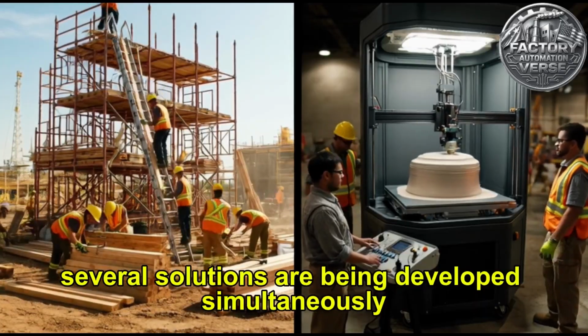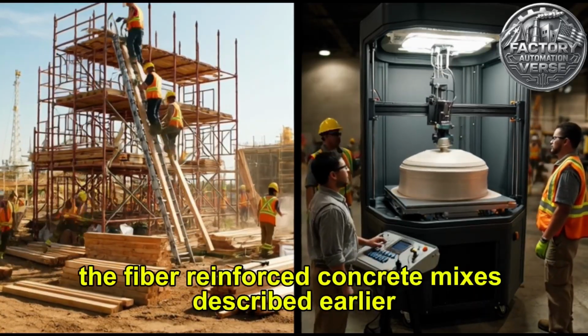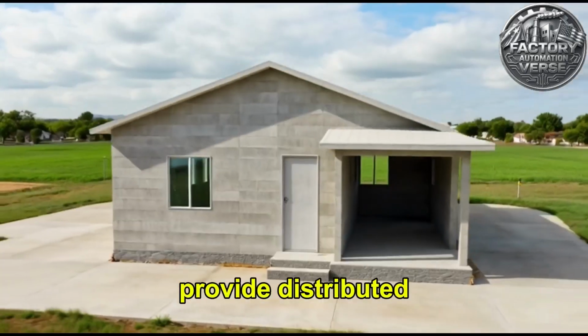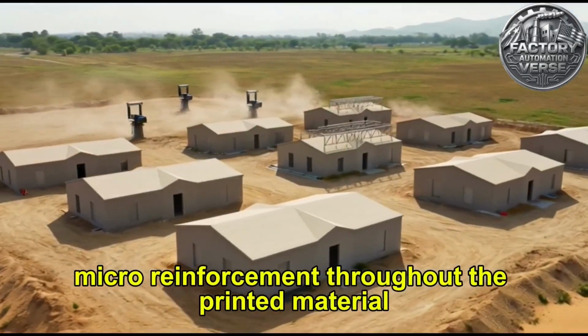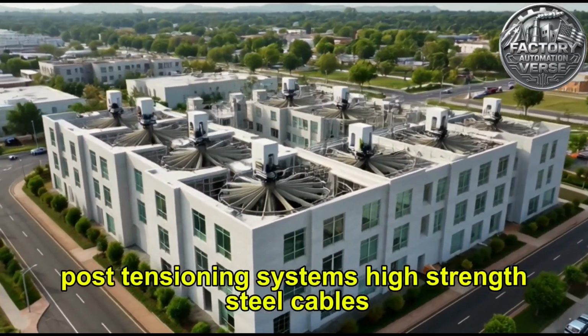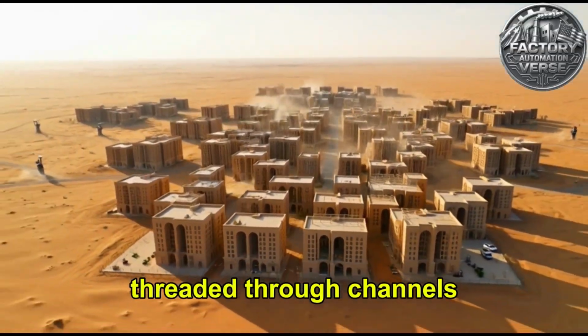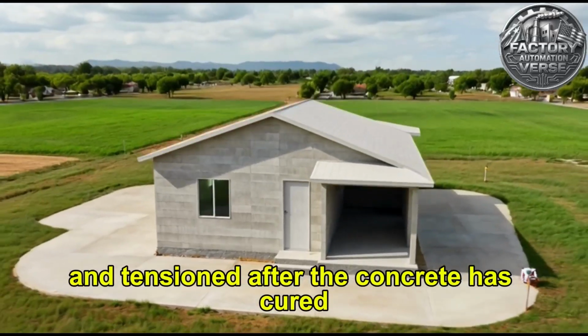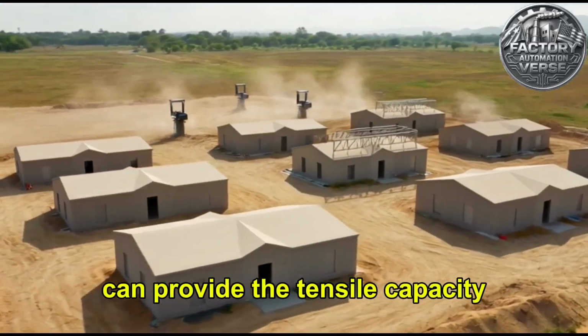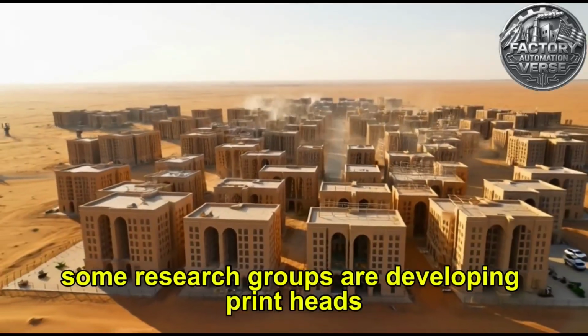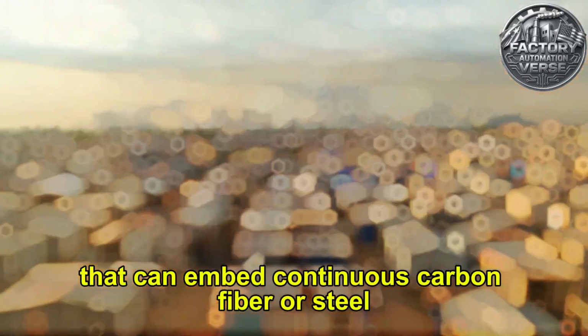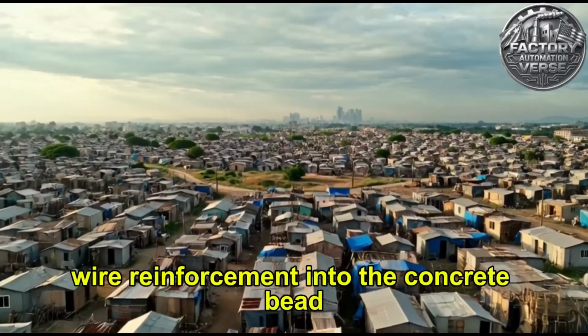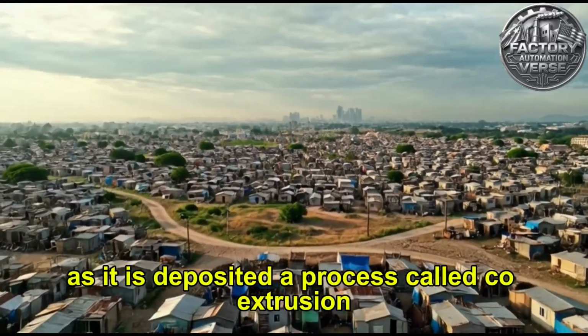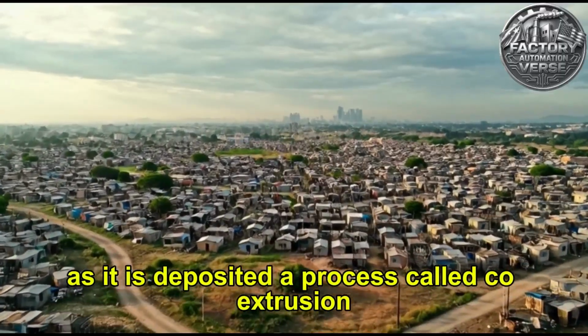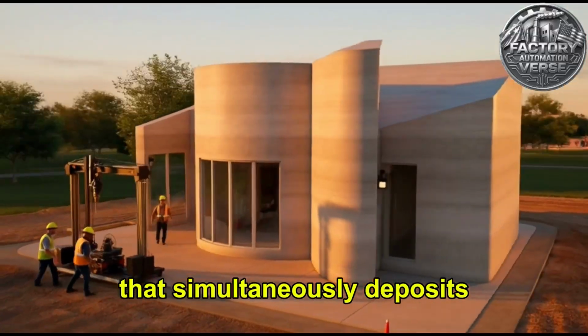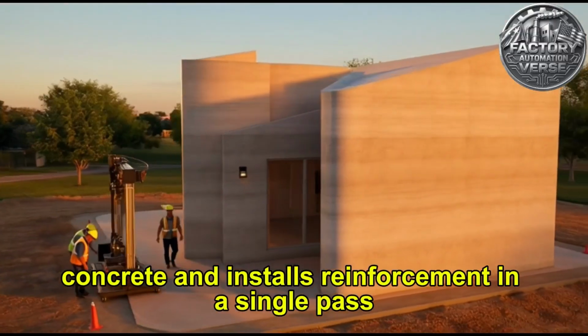Several solutions are being developed simultaneously. The fiber-reinforced concrete mixes described earlier provide distributed micro-reinforcement throughout the printed material. Post-tensioning systems, high-strength steel cables threaded through channels left in the printed structure and tensioned after the concrete is cured, can provide the tensile capacity needed for structural spans. Some research groups are developing print heads that can embed continuous carbon fiber or steel wire reinforcement into the concrete bead as it is deposited, a process called co-extrusion, turning the printer into a machine that simultaneously deposits concrete and installs reinforcement in a single pass.